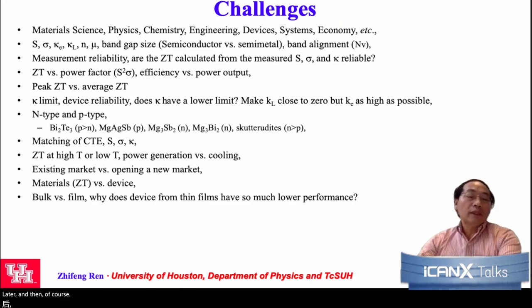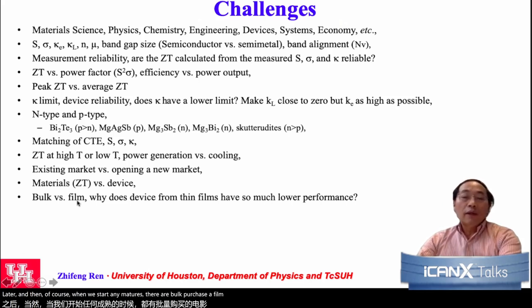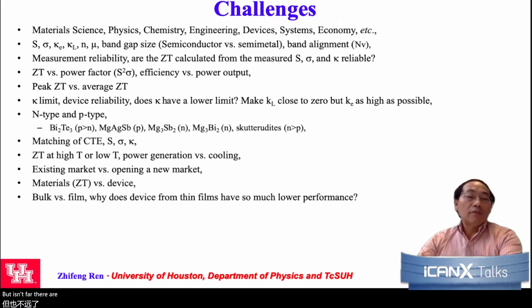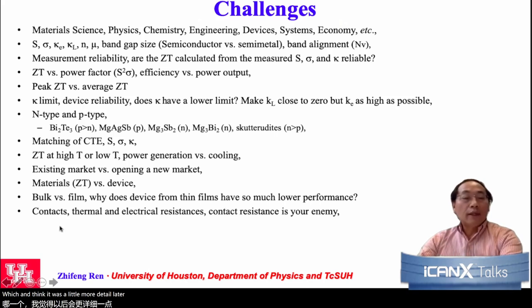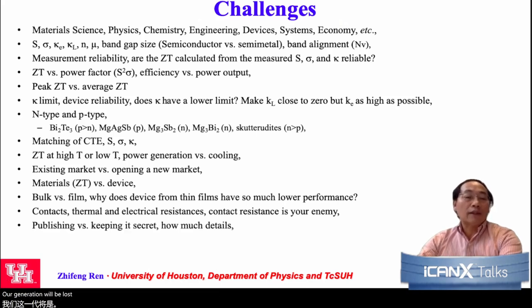And then, of course, when we start with any materials, there are bulk versus film. Even though film could have very high ZT, so far the delta T demonstrated by film is not even as good as bulk. Why is that? I'm going to talk about that in more detail later. And of course, there are contact thermal and electrical resistances. Contact resistance is really your big enemy. You have to reduce it, otherwise your generated power will be lost at the contact.